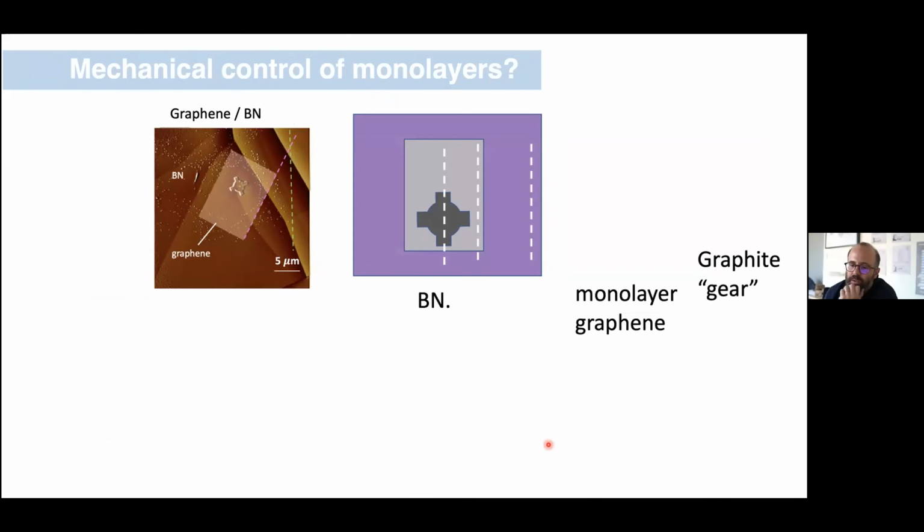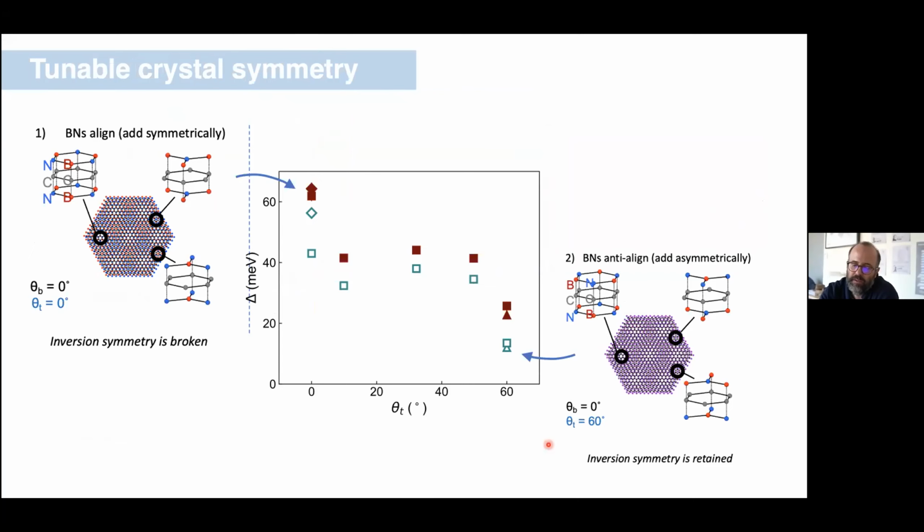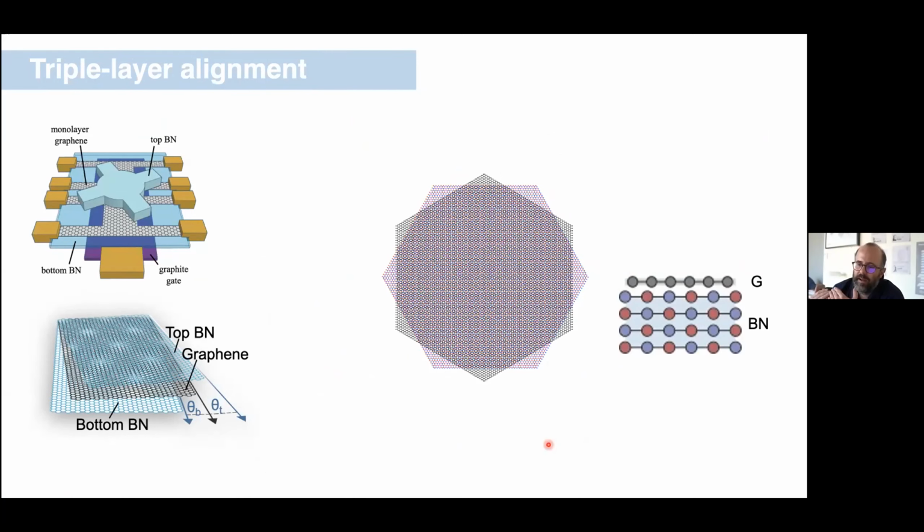Yeah, absolutely. So what we do know is, I skipped a bunch of details here, but when we measure graphene on BN, graphene BN is not actually lattice commensurate at all. So one of the questions you might ask is, should you or should you not have a band gap in the system? One of the first theory answers was, if you imagine graphene and BN are coupled and you assume their lattices were exactly matched, then the two sublattices that Stefan introduced, A and B sublattices, would see different potentials. One would see a boron atom and one would see a nitrogen atom. And that would be enough to break the sublattice degeneracy of graphene and open a gap.